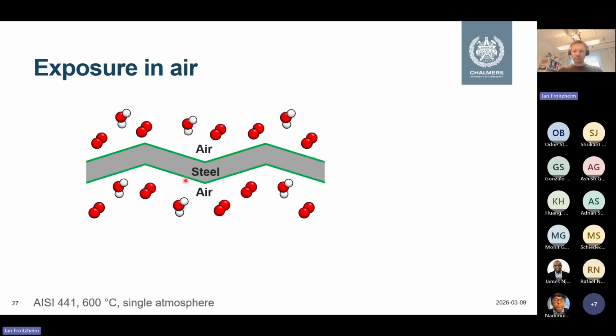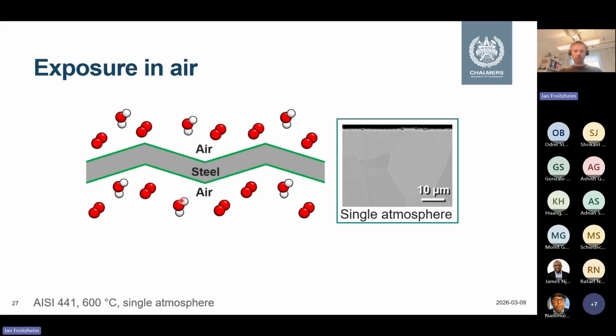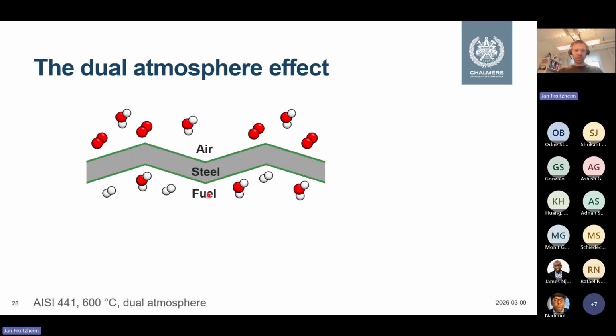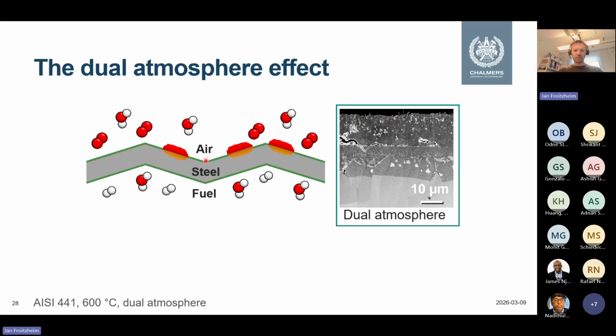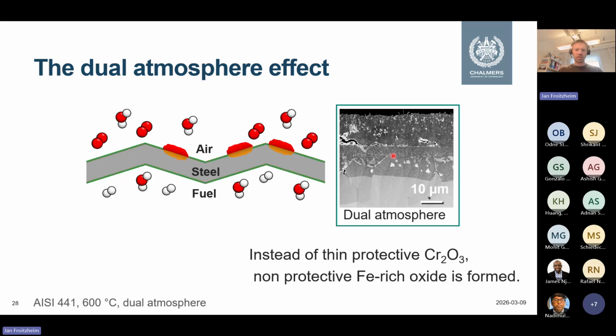So to summarize, basically in air, if we have air on both sides, we get a thin protective scale, and the oxide scale is a couple of 100 nanometers, basically. While if we have fuel on one side, it's the air side that is affected with this fast-growing iron-rich oxide, and the sample looks like this, and you get like 30 microns of oxide scale or so, depending a little on how long you run it. So it's a massive difference - instead of this thin protective chromia scale, we get non-protective iron-rich oxide.